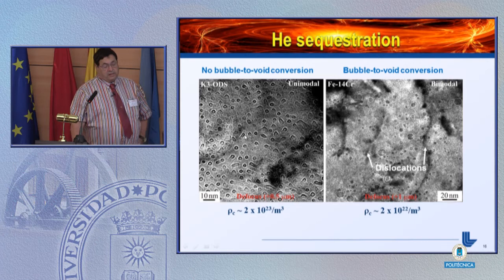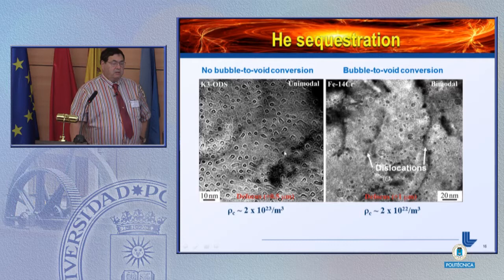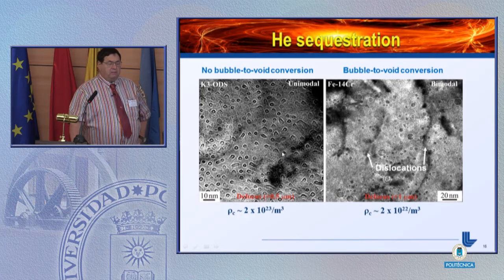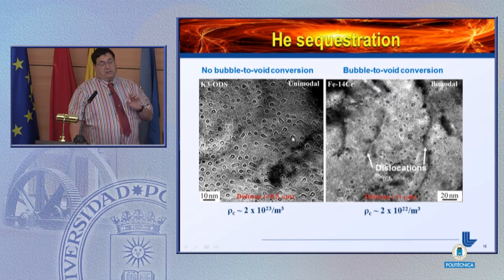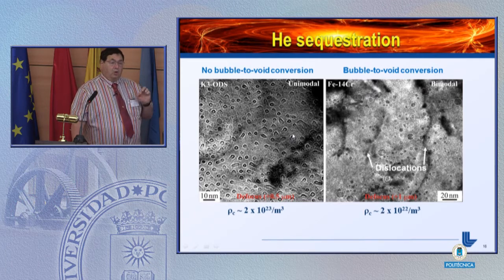And the reason we call them bubbles is that all of these cavities that are here are below what is called the critical size. The critical size is the radius at which the cavity transitions to a growth mechanism which is driven by a diffusional bias between interstitials and vacancies. Once you've reached critical size, this is an unconstrained growth process. In other terminology, this is called the incubation phase. And the more nucleation sites you have for these little bubbles, the longer that incubation phase will last, and the smaller the swelling per injected helium will be.